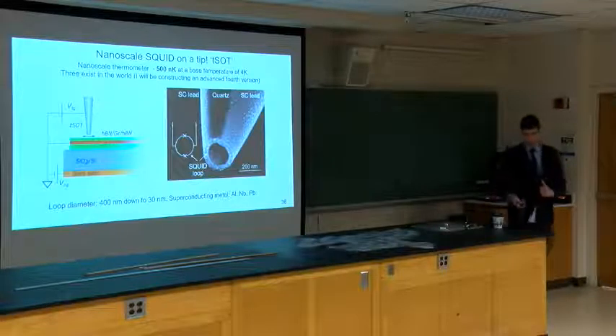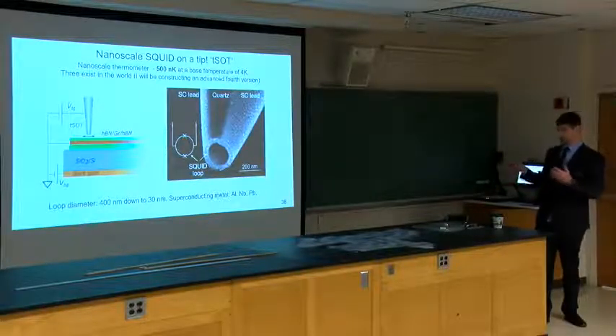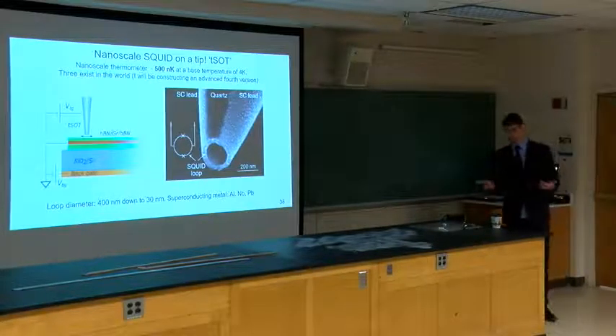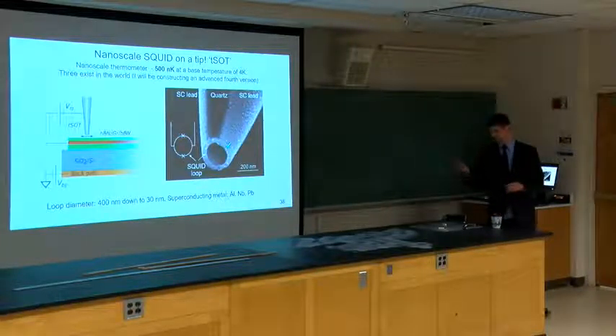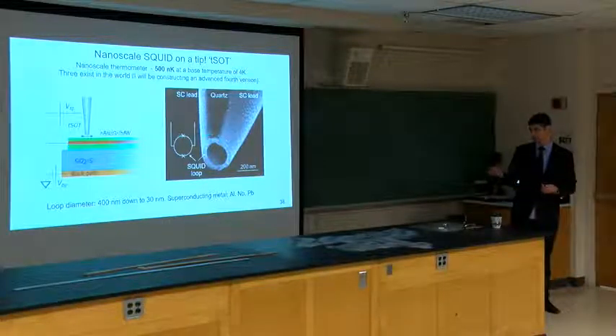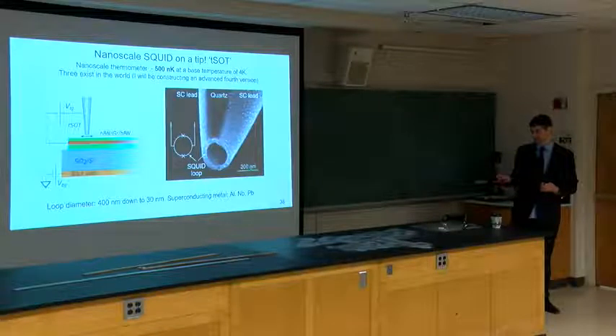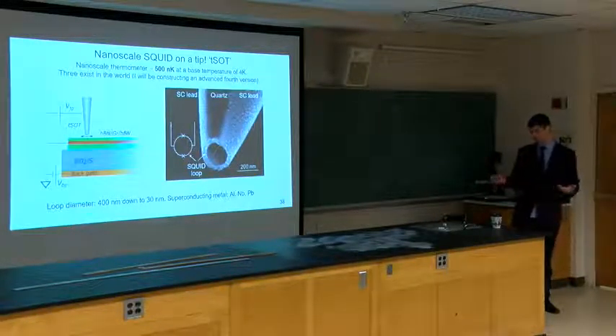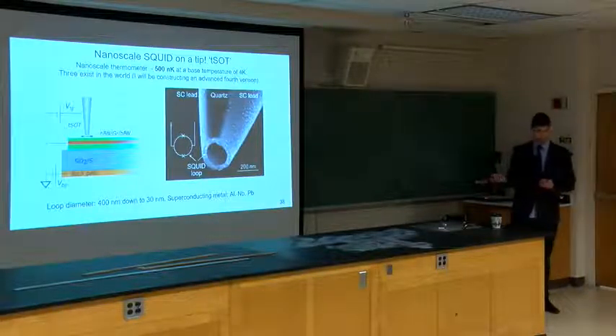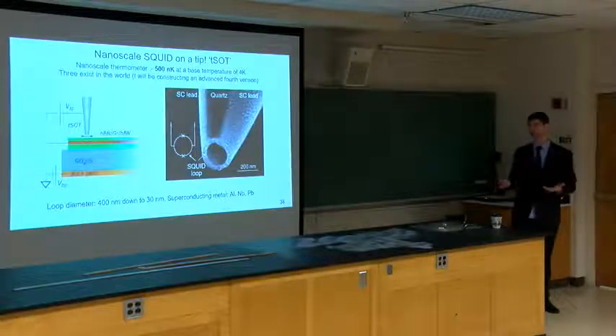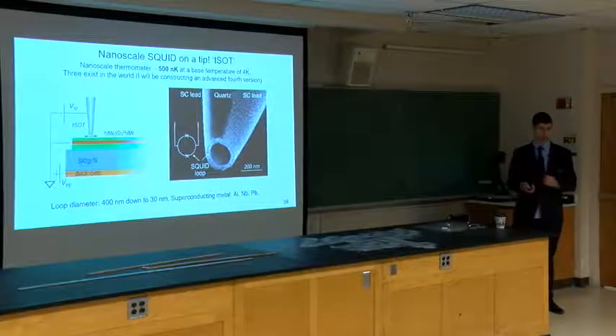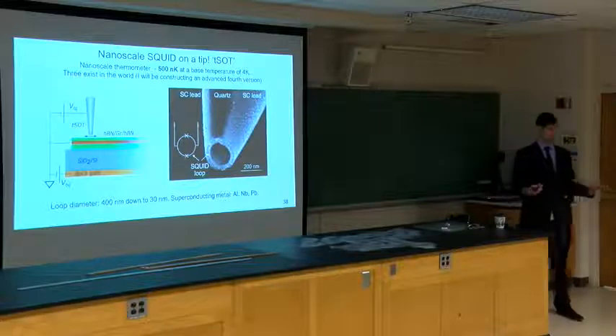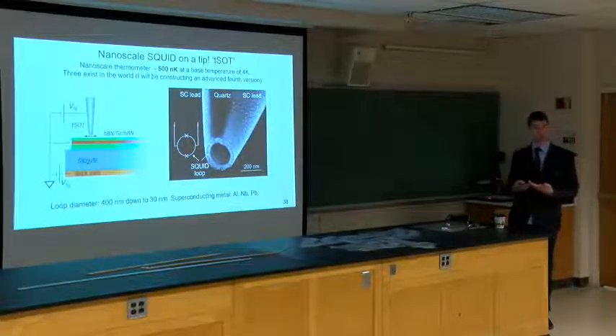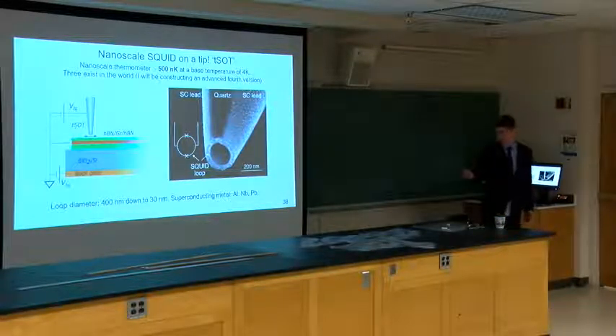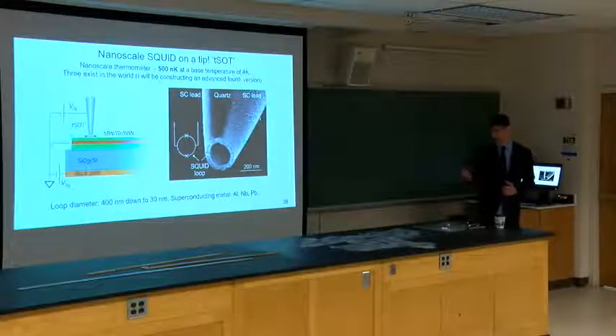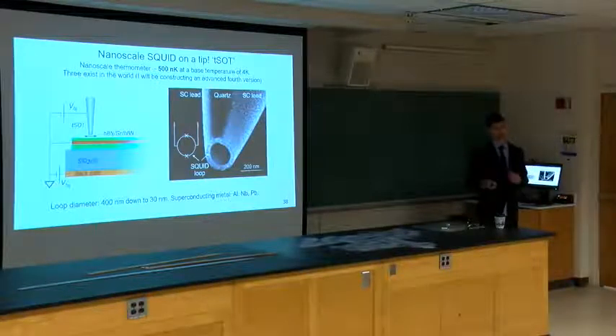So to look at this, I collaborated with a group in Israel, and we used what we'll call a nanoscale SQUID on a tip, or a scanning thermometer, basically. It's a quartz pipette with superconducting metals deposited on the edges, with a SQUID loop at the base of the tip. So the loop diameter can be very small. You can use a lot of superconducting metals for this: aluminum, niobium, lead. Lead typically had the lowest noise level, so that's what we used. You also need a material with a transition temperature high enough that we can actually look at physics beyond, we need to go to the quantum Hall effect, right? So we need to be able to go at least near a Tesla. So basically, we scan this equipment across the surface, and you can apply a top gate to this, and also measure if there are any temperature changes in the system.